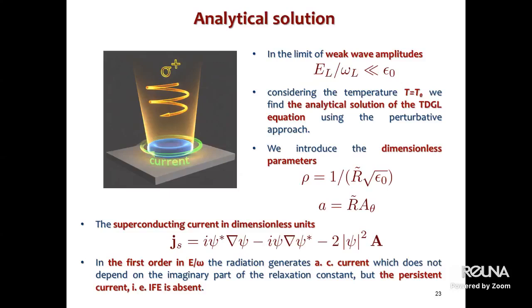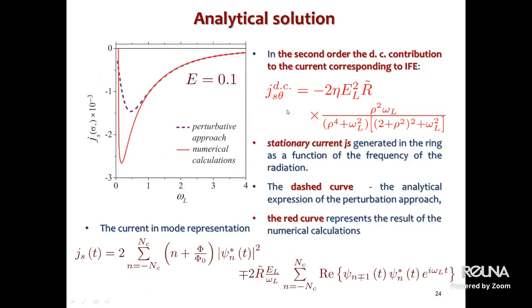That means we need to go to the next level of perturbation. In the second order of perturbation, we can find the constant or persistent or DC contribution to the current, and it corresponds to the inverse Faraday effect. This figure shows the stationary current generated in the ring as a function of the frequency of the radiation with constant amplitude.